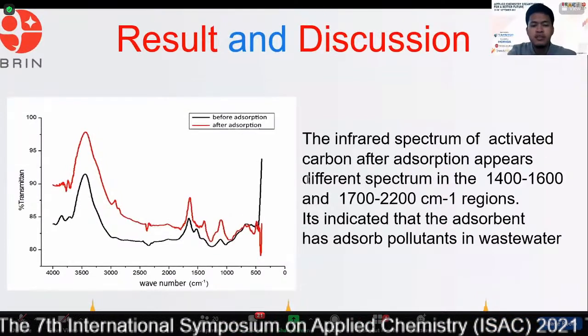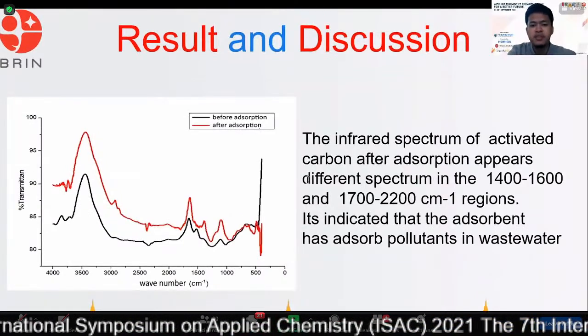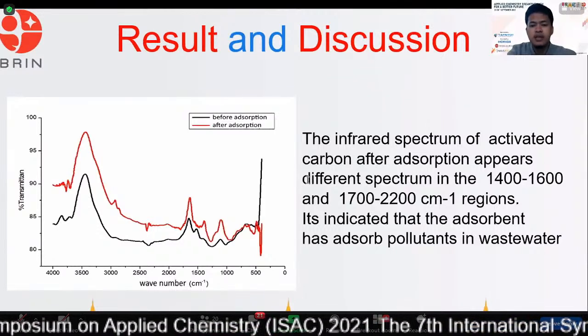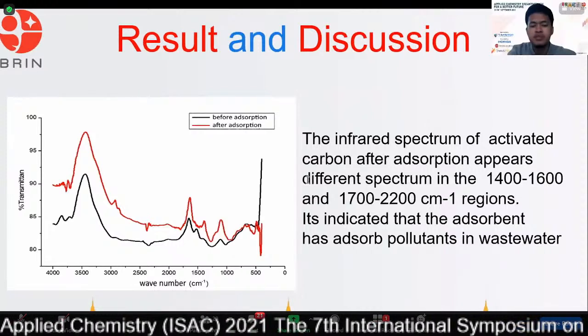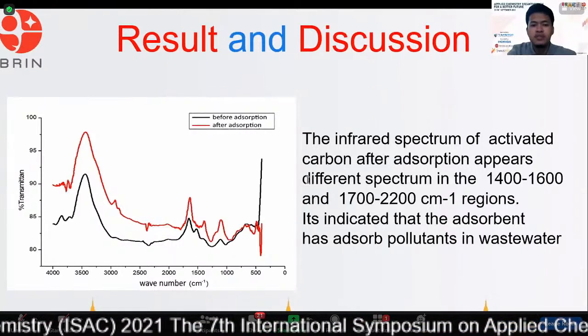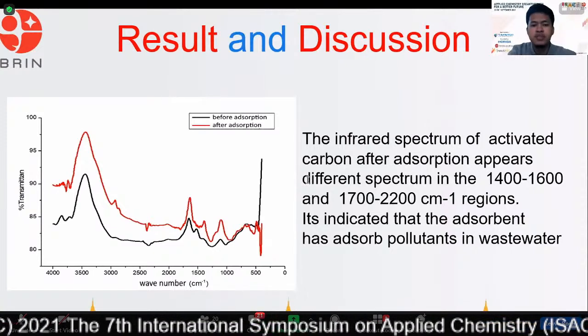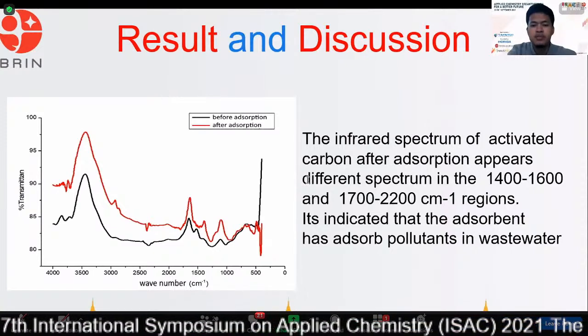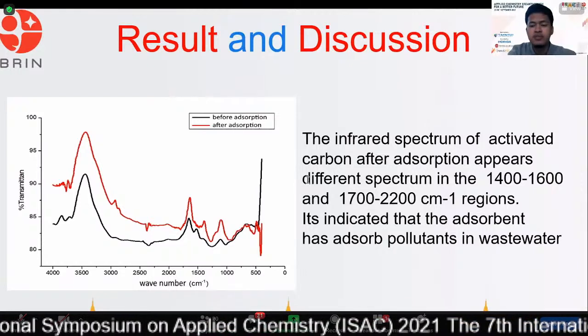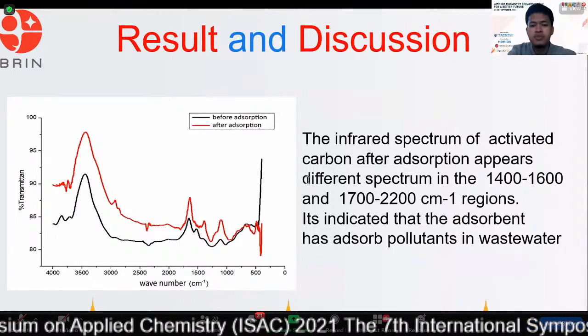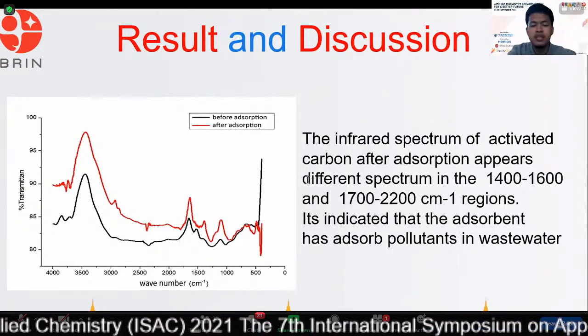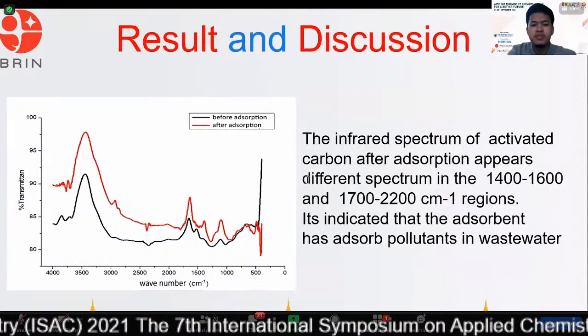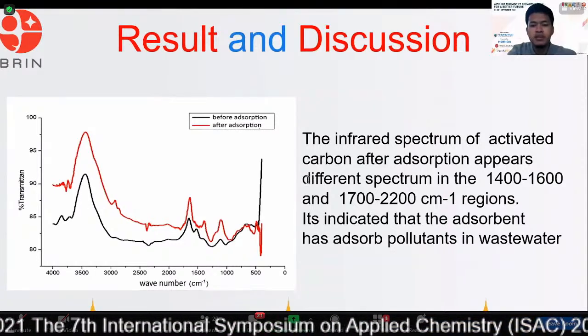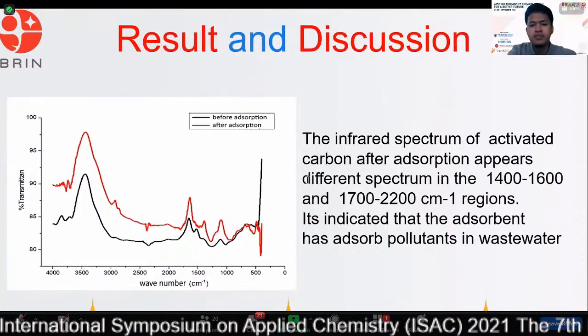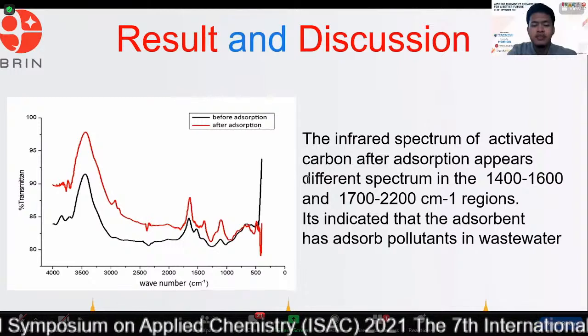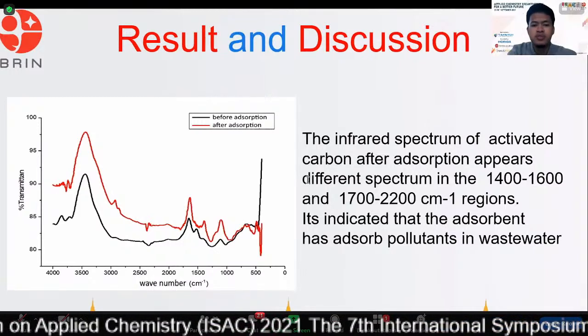Okay, this is the FTIR analysis for the activated carbon in use after and before the absorption process. We can see there is a difference in the spectrum in the peaks at 1,400 until 1,600, and at 1,700 until 2,200. The difference peaks in this picture can prove that the activated carbon absorbs the pollutant in wastewater.